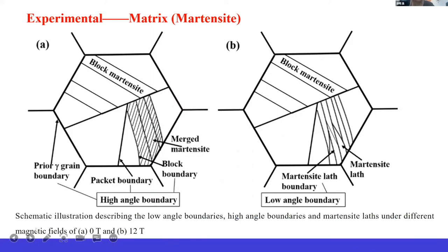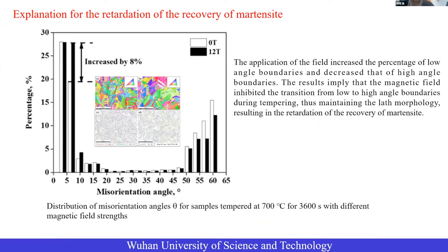So we draw the schematic illustration describing the low angle boundaries, high angle boundaries, and martensite laths under different magnetic fields. The right picture shows that the low angle boundaries increase. So we did EBSD to prove that. Finally, the misorientation angle from 5 to 10 degrees, the percentage increased by 8%. This is the reason we can explain why the external field retards the martensite recovery.